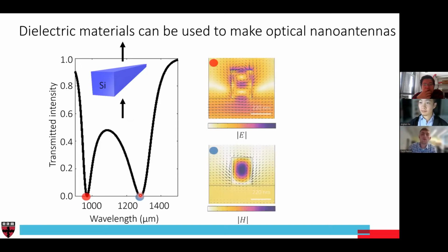And if we zoom in and actually simulate what this response looks like, this rectangle structure is the silicon that we were talking about, sitting on a substrate. The plots here are either the electric or the magnetic field of the light locally in the material, and these arrows show the relative field orientation. What we find is that the red and blue regions that correspond to these dips are optical resonances that mimic the look of various dipole sources.